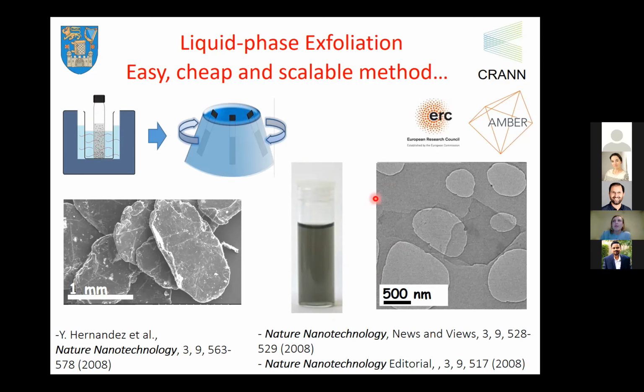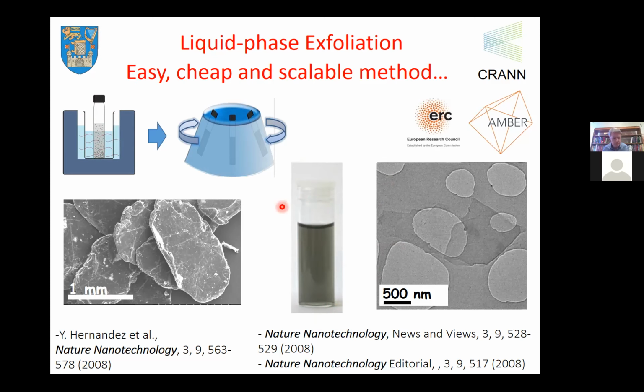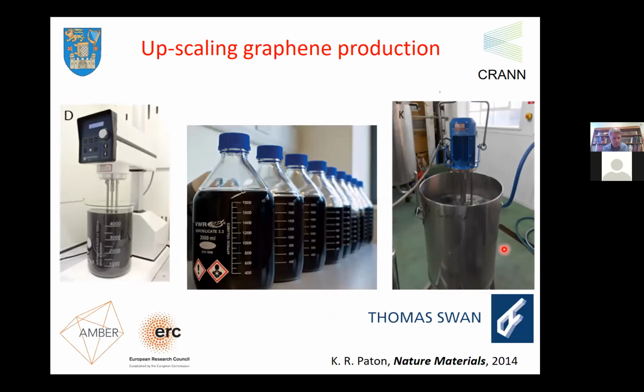Now I have this vial still in my lab as a momentum, a sort of capture of time. It's still in the same condition. If you look at the microscope, you will see that it's a very successful exfoliation. You get single layers, some multiple layers, but effectively it was a very, very simple methodology that opened a huge amount of work that followed up, because it opened up a lot of different possibilities of processing these materials that we didn't have before.